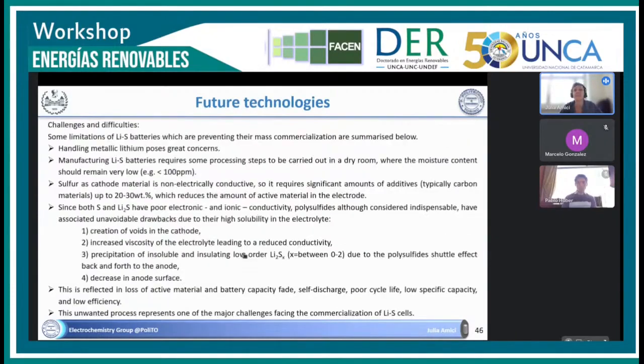The problem is that these lithium polysulfides I was talking about are easily dissolved inside the electrolyte. One, the viscosity of the electrolyte increases a lot, making the conductivity decrease. And two, they can directly react with the lithium metal and passivate it. So the problem of the lithium polysulfide is very important in the research for lithium sulfur technology.